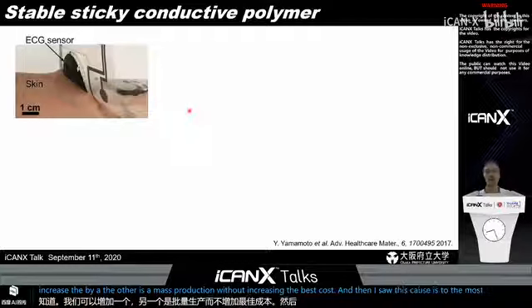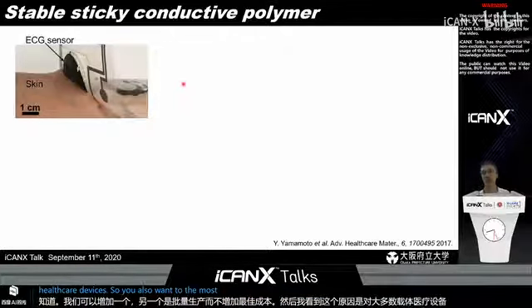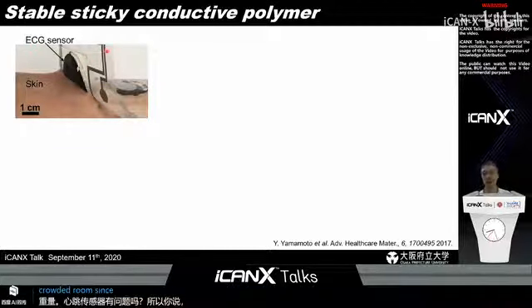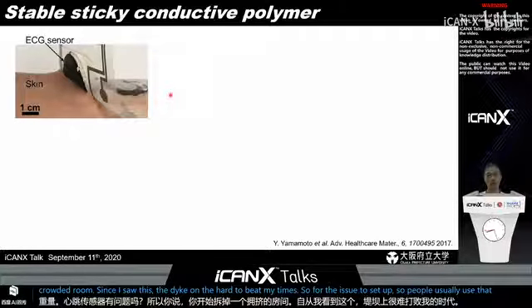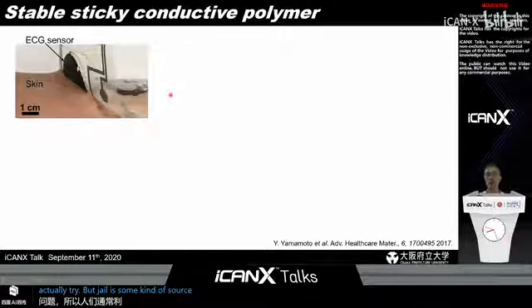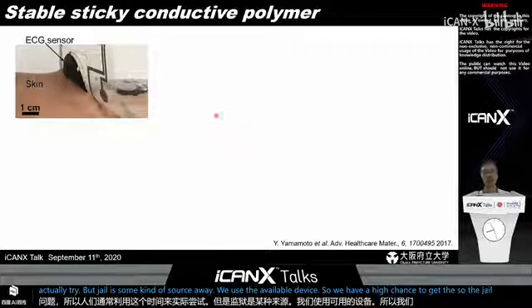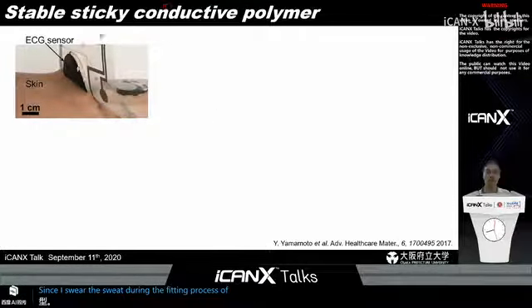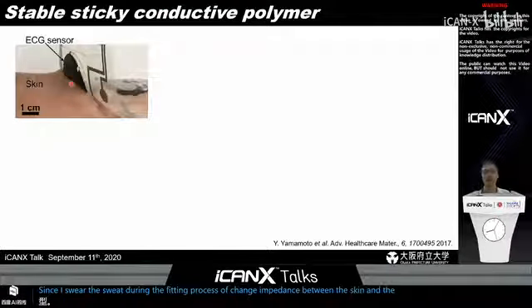Since our focus is to demonstrate healthcare devices, we also want to demonstrate the ECG, the heartbeat sensors. ECG stands for electrocardiogram sensor. This is like heartbeat monitoring. For the ECG sensor, people usually use the gel type electrode. However, when we use a wearable device, we have a high chance of getting sweat, and the gel type sensor swells with the sweat. During the sweating process, the contact impedance between the skin and the gel is drastically changed, so it's very hard to measure the ECG under sweat conditions.